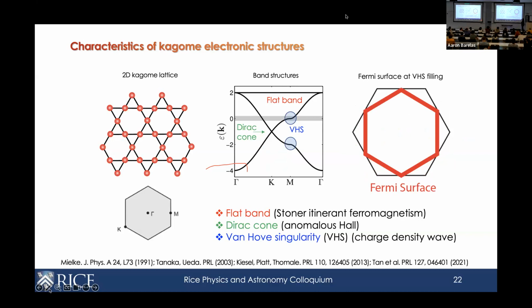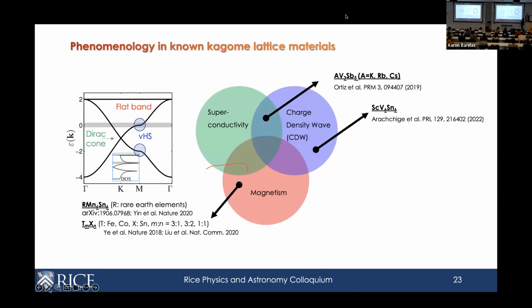It looks like this hexagon, and from this, you see there are 3 pairs of parallel sections of the Fermi surface which are connected by the same wave vector, and this will give you an instability, which is called a charge density wave that will actually fold the Brillouin zone and produce a wave in the density. It's like a stadium wave, right? And so these are the predictions of a 2-dimensional Kagome lattice. So, okay.